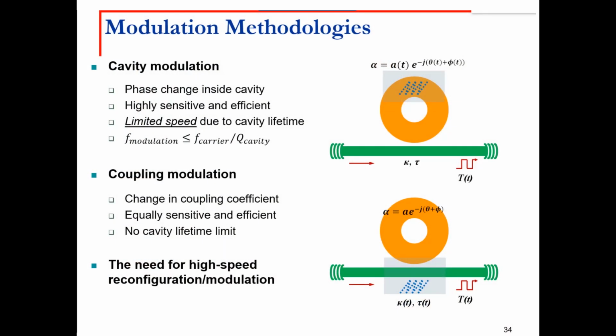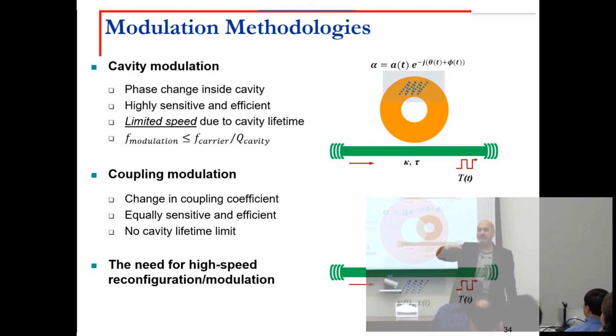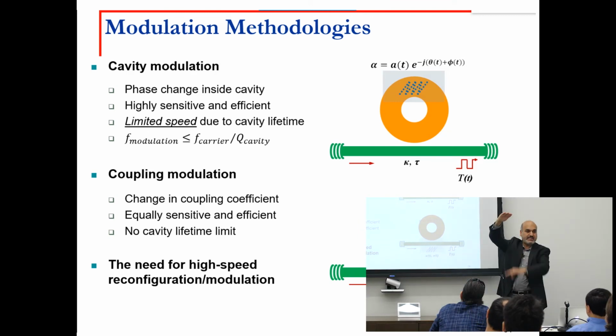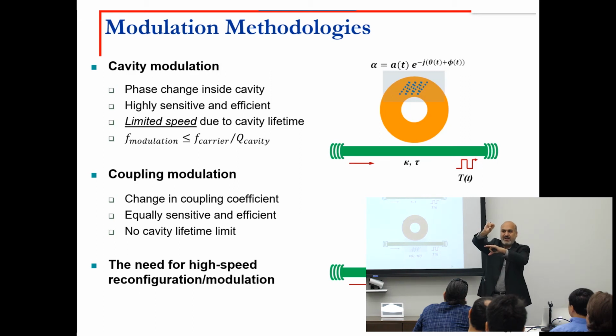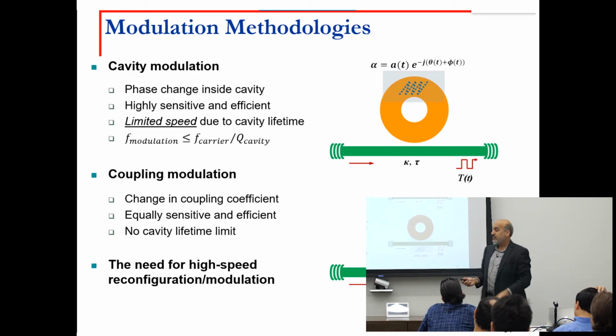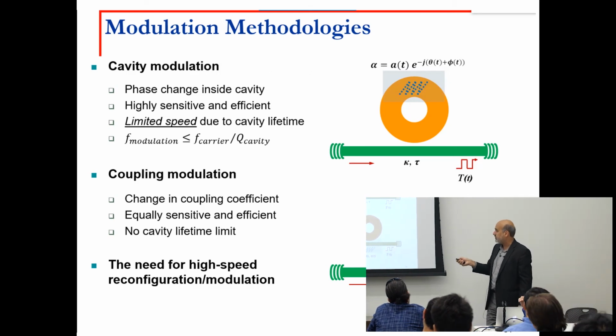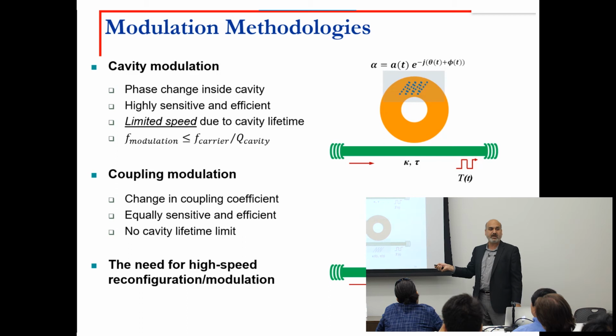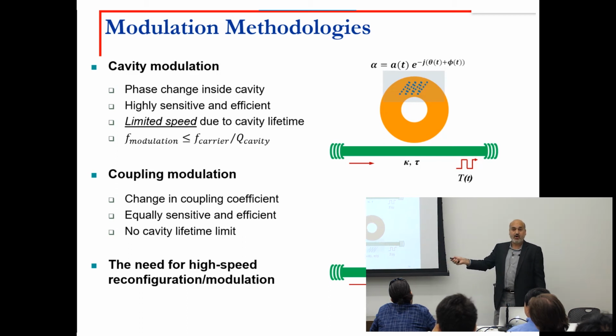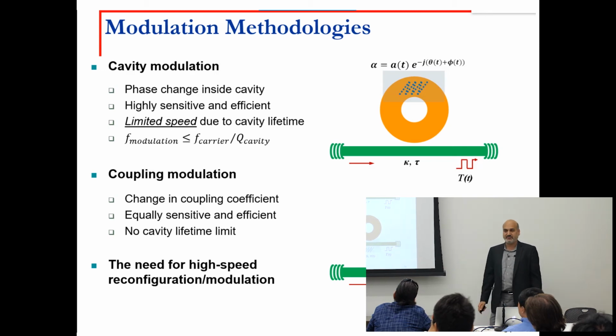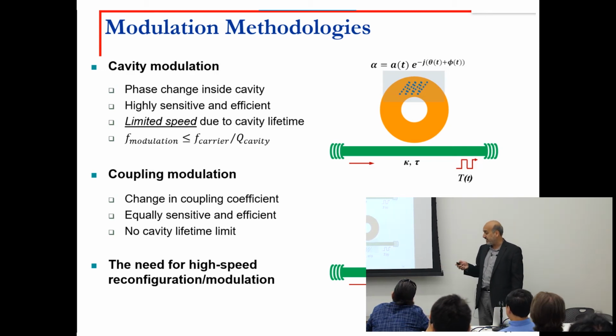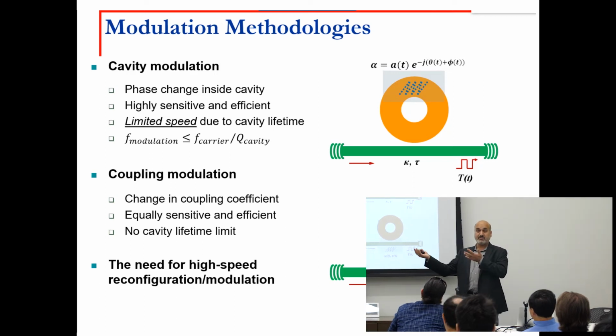Now, in the second example, what we do is we don't touch the resonator. It's a fixed resonance. All we do is change the coupling of light from waveguide to resonator by a small amount, meaning that in that dam example, I just bring the wall down a little bit and up a little bit. So I don't empty my dam. I just bring it down and up for enough signal or enough water to get into my channel. Remember that the signal in the resonator is thousands of times larger than that in the waveguide because it develops over time. So all I need is just a tiny change in the coupling coefficient in order to get my modulation. This way, we break the trade-off between power consumption and speed.